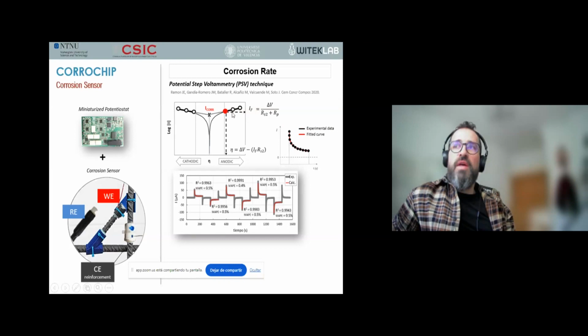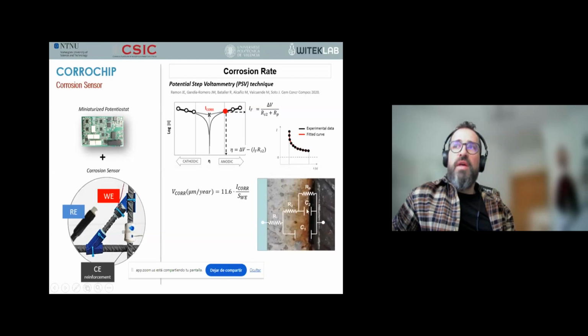Each point on the Tafel lines is obtained by modeling the system response to the pulses by using a curve fitting with a specific equivalent circuit. So the value of the ordinate corresponds to the Faraday current passing through the model at that state, whereas the abscissa corresponds to the applied potential, which is obtained by subtracting the ohmic drop from the applied potential. So the corrosion current finally is obtained by the intercept of the lines.